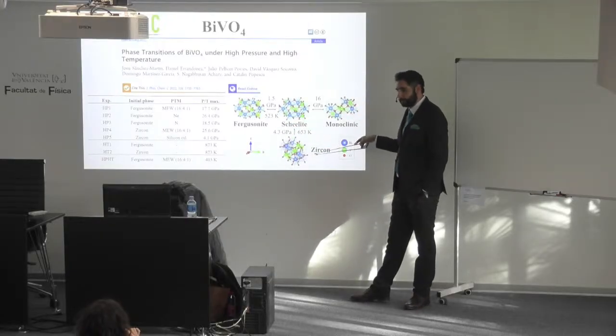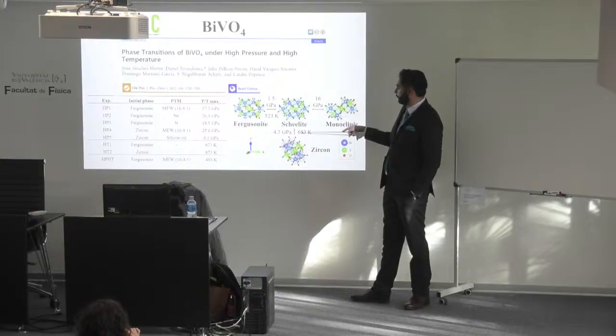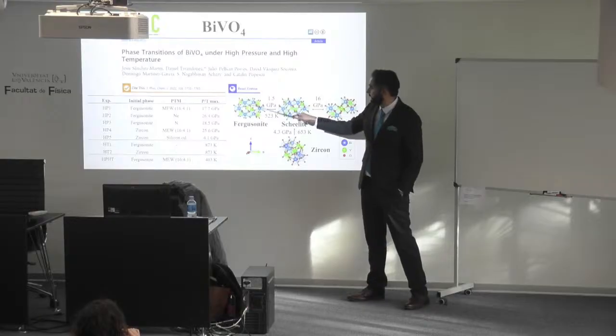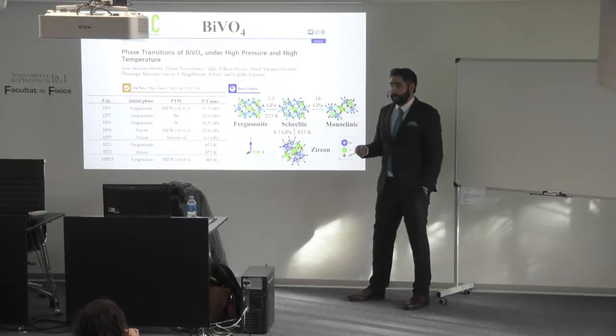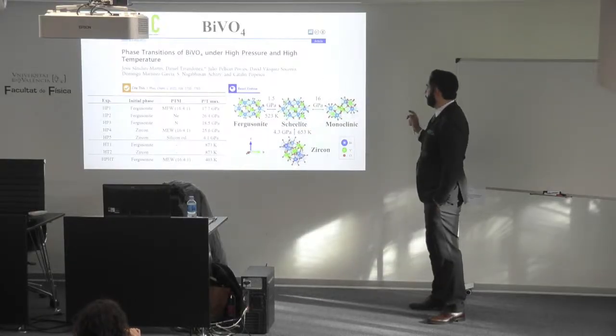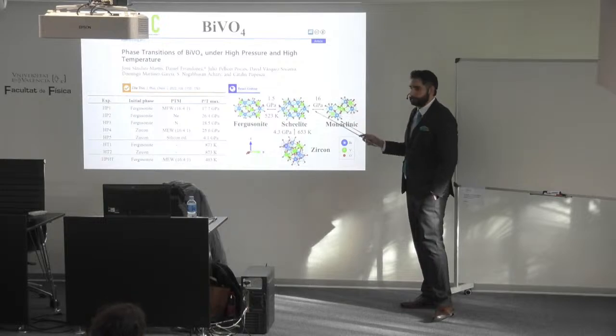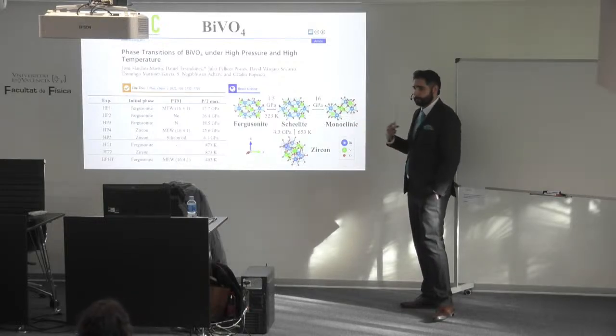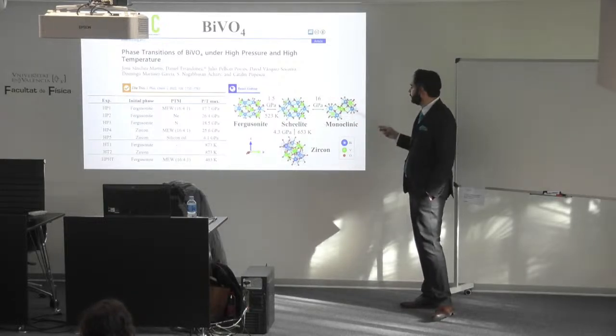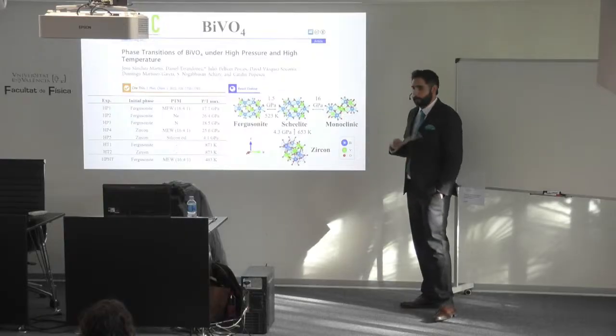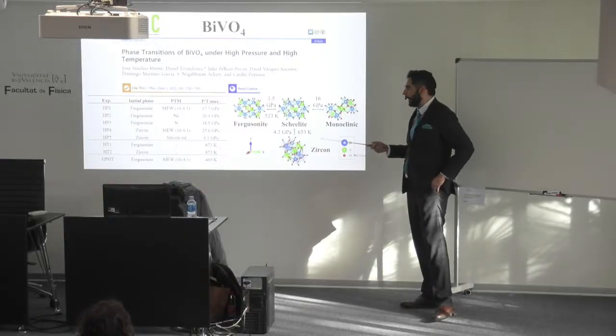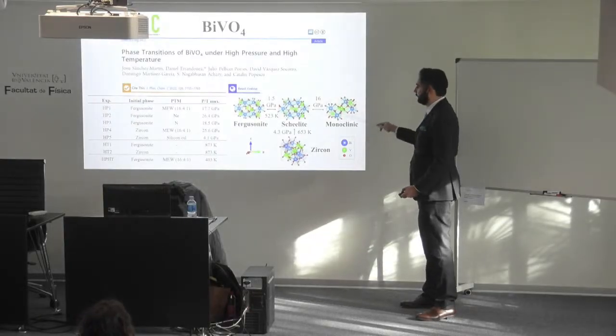Okay, so we can get this at ambient conditions, but once we apply pressure or temperature, it goes to scheelite and it's not reversible. The reversible one is the fergusonite. And in this case also, we found at 16 gigapascal that it has another phase transition into a monoclinic structure, and I will explain later why the results are not that prolific for this structure.